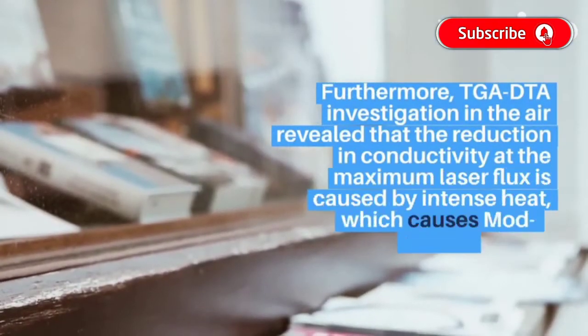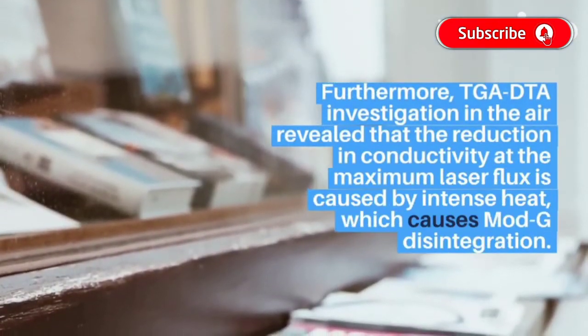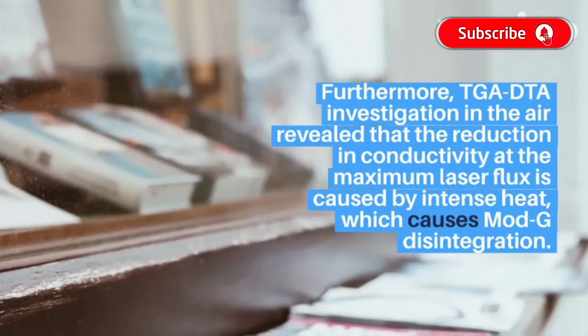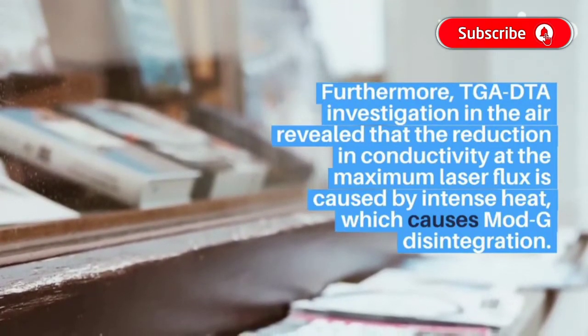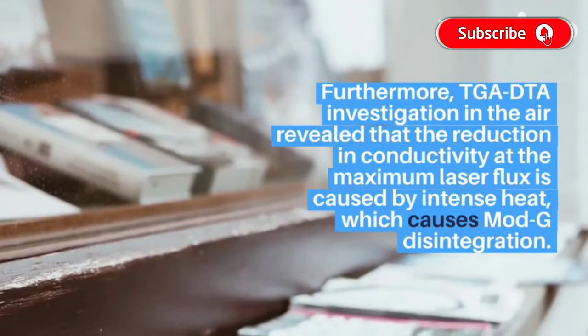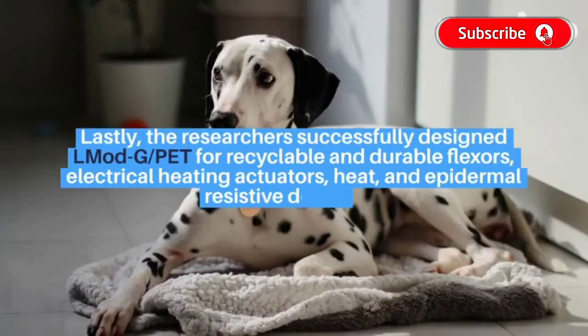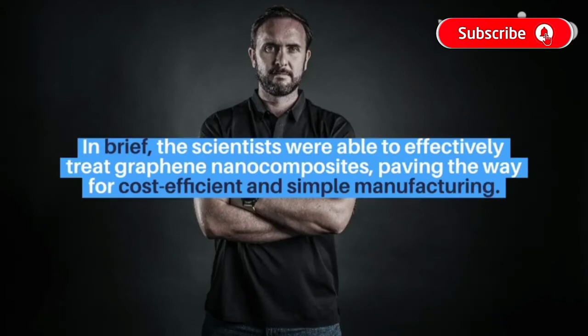Furthermore, TGA-DTA investigation in the air revealed that the reduction in conductivity at the maximum laser flux is caused by intense heat, which causes Mod-G disintegration. Lastly, the researchers successfully designed Mod-G PET for recyclable and durable flexors, electrical heating actuators, heat, and epidermal resistive detectors. In brief, the scientists were able to effectively treat graphene nanocomposites, paving the way for cost-efficient and simple manufacturing.